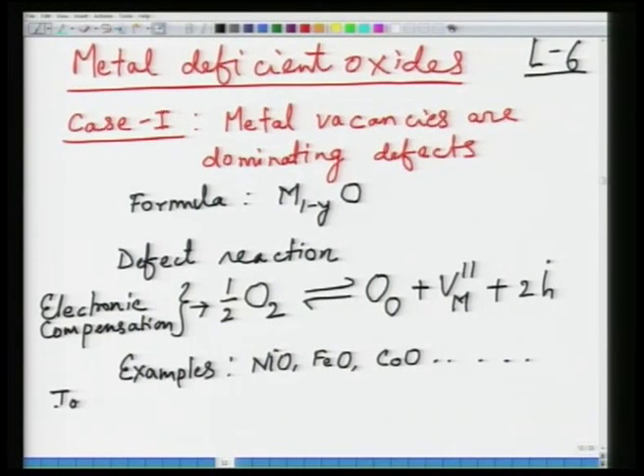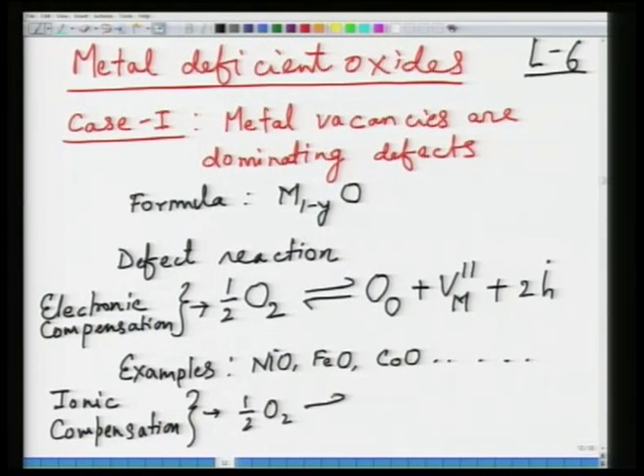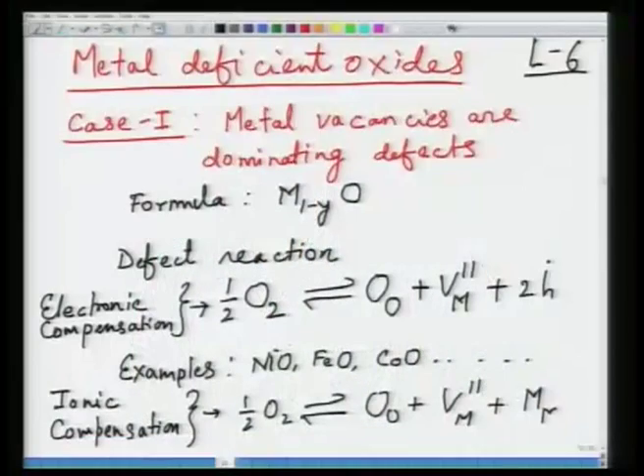If you have ionic compensation, this would mean half O2 going to an oxygen site, with a complementary metal site which is vacant. Now, unlike in the previous case where metal reduction occurred, here you may have metal oxidation. So, metal on a metal site, if it was oxidizing to an extra +1 state, then this would be 2 M dot. So, basically what it effectively means is that this is equal to 2 of M3+.